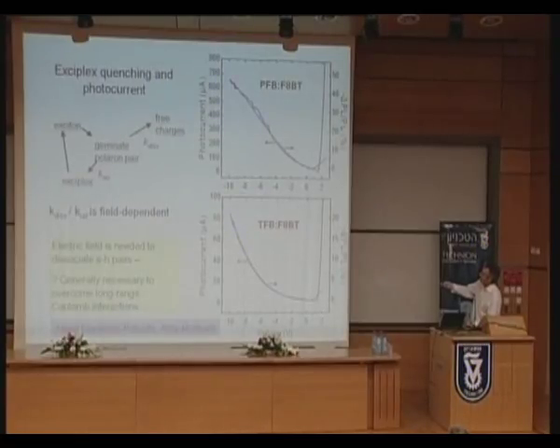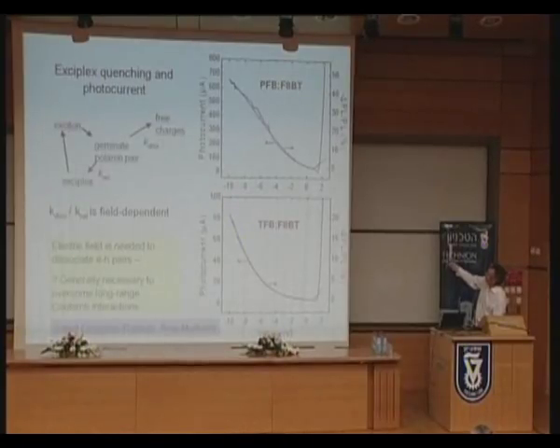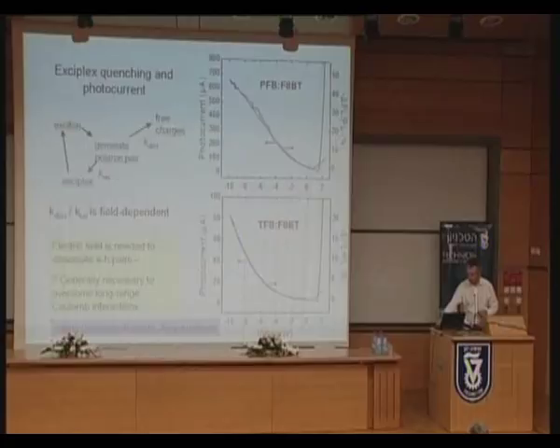So it's when we have, well, the jargon here is a geminate polaron pair, where the presence of a DC field biases it towards free charges rather than this bound exciplex. And a way of seeing this very clearly is if we plot as a function of bias voltage, this is reverse voltage across the diode, 0 through to minus 10 volts, and we look at the photocurrent, which is the red line. In forward bias, we get charge injection, and the current takes off. That's not important. And then look at the blue line, which is this fractional quenching of the exciplex luminescence. The two lie on top of one another. So if we quench the luminescence, we get charge in the external circuit.